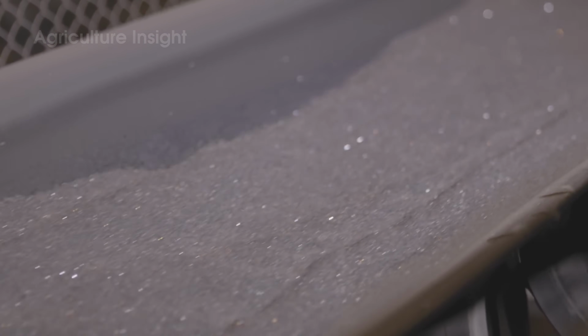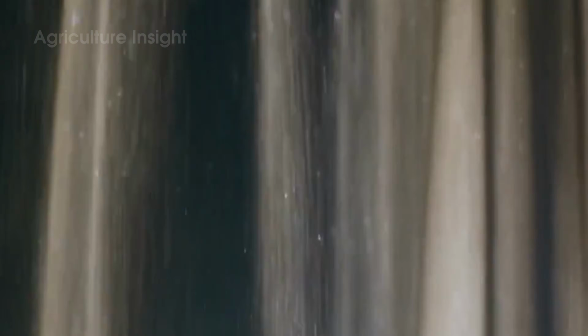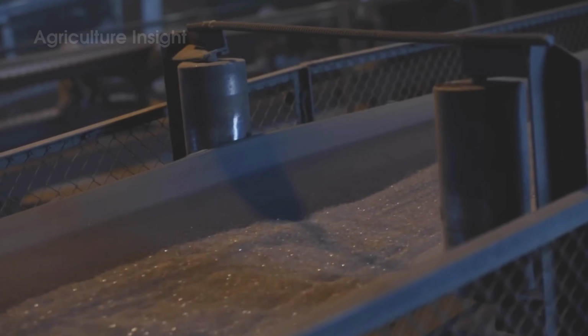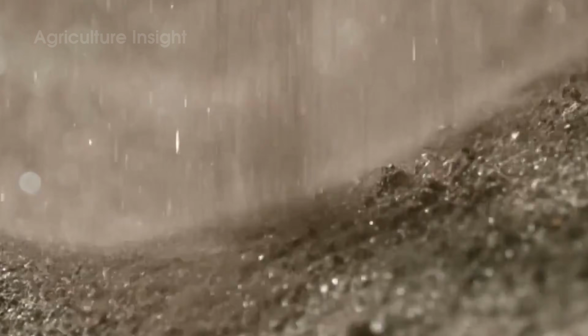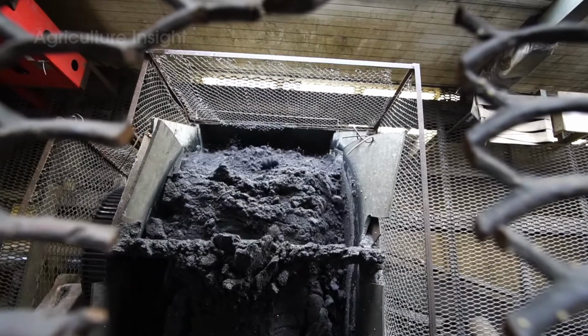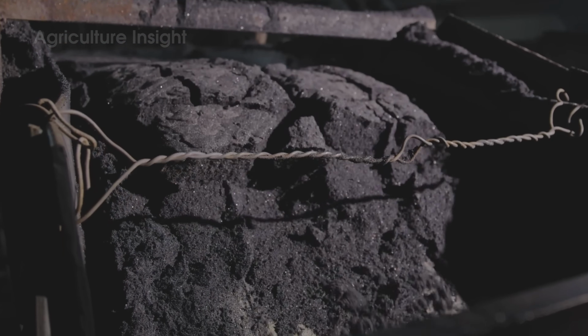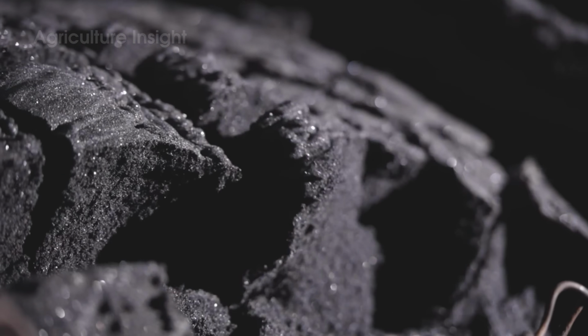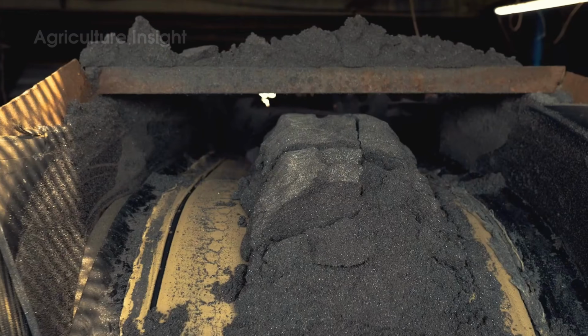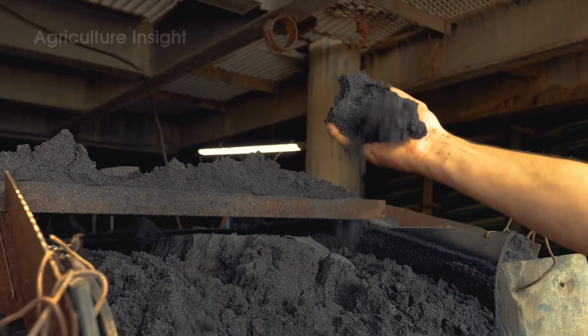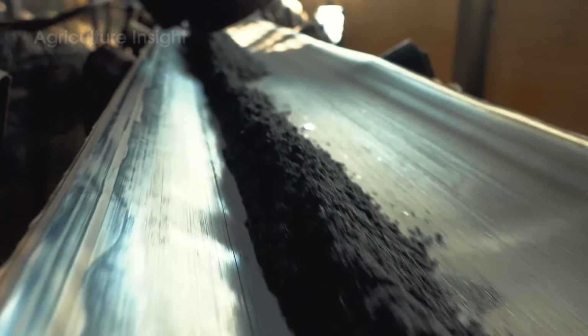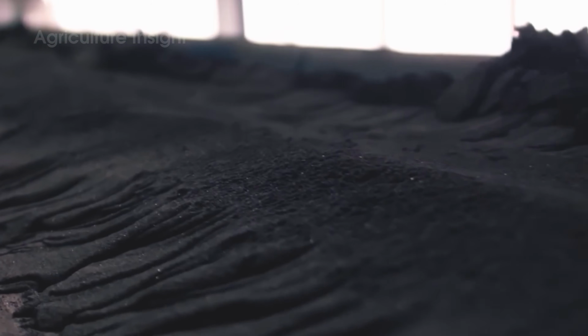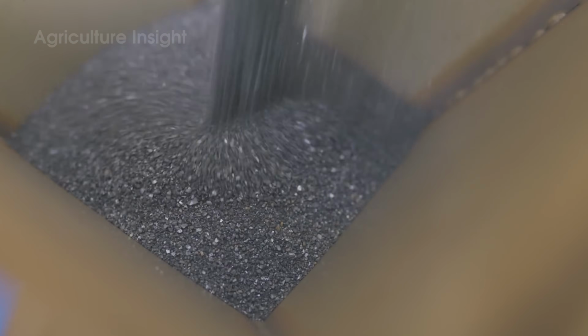Notably, from 1 ton of initial placer sand, engineers typically recover only about 30 to 80 kilograms of titanium concentrate, while the remaining material is returned for environmental rehabilitation. This low recovery rate, combined with the multi-stage processing required, is why titanium, despite being abundant in nature, remains relatively rare and highly valuable in industrial applications.